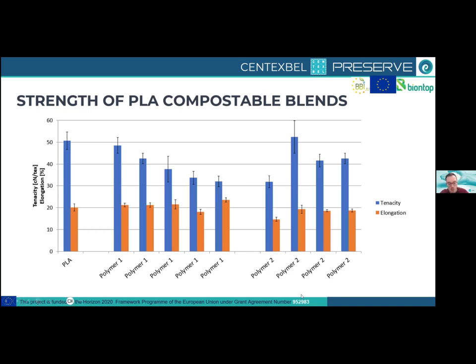Polymer 2 is another, a different polymer. And here it is not the weight percentage that we looked at, but only the grade. So we have different types of grades where the polymer itself is different, but the type of polymer is the same. And then we can see that with the different grades we also see different strengths and also different compostability levels.